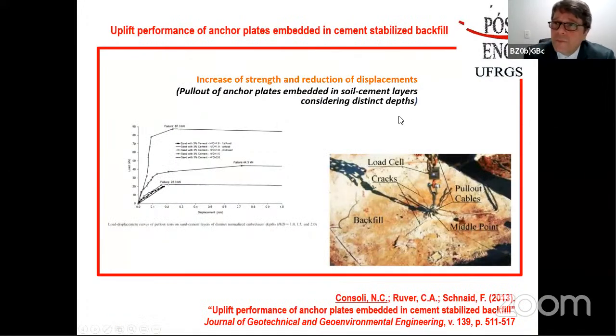When I came back from this sabbatical, and before going to another one in Bristol, it was interesting because we carried out similar tests, but in the field, in real size. So we have here some backfill that we have done with cement and in different thicknesses of this layer. And we could find similar results in the field, confirming the results that we had found. We increased a lot, and the influence of the depth was quite well shown in this case. This was published in the Journal of Geotechnical and Geoenvironmental Engineering in 2013.